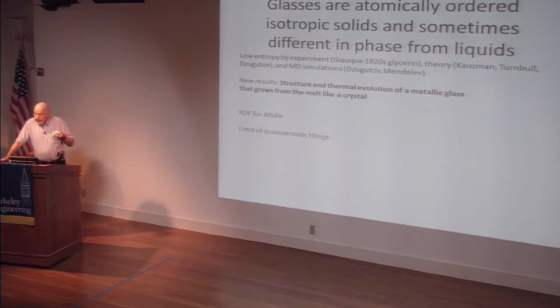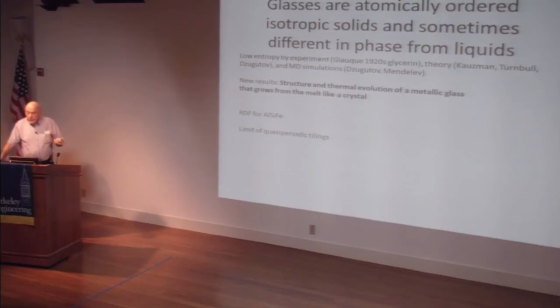He unfortunately used a very poor model for his thing, but the fact that this exists is fascinating, that you can have an isotropic solid phase different from the liquid. And so this is my most recent work, Structure and Thermal Evolution of Metallic Glass that Grows from the Melt Like a Crystal. We found this as a failure when we were trying to make quasi-crystals in '88.